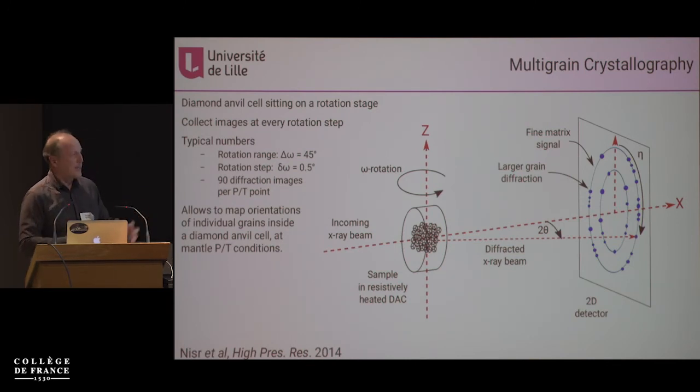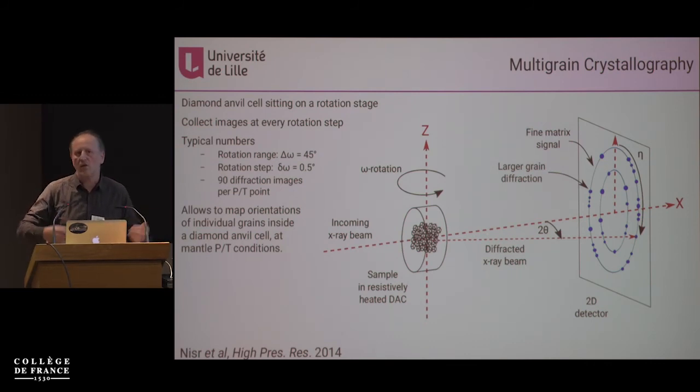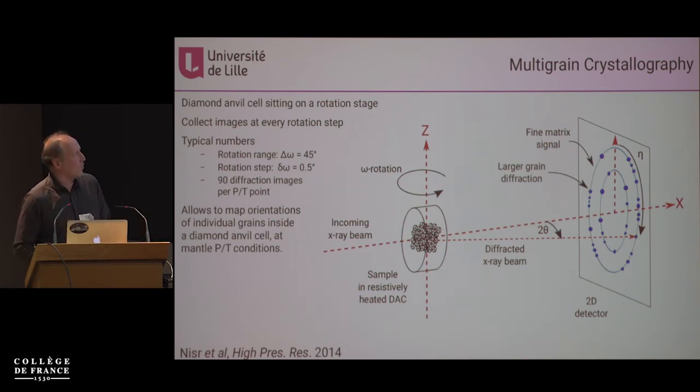And so there is a technique which involves basically a tomography of diffraction, where you reconstruct the 3D features of diffraction of your sample. So you step scan the sample in front of an X-ray beam, you look at how the diffraction pattern changes with rotation, and you can reconstruct the microstructure.